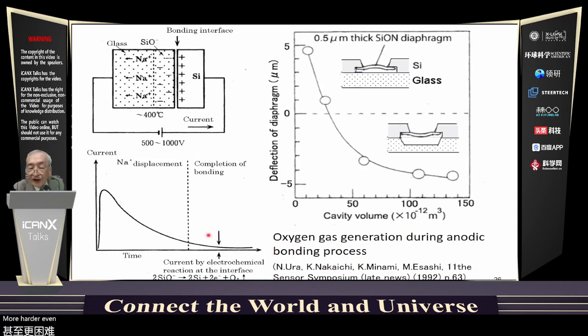This current is caused by electrochemical reaction of the SiO minus at the interface, which generates oxygen gas. The right graph shows the evidence of the oxygen generation. A silicon wafer having thin SiO and silicon oxynitride diaphragms and cavities was anodically bonded to a glass wafer in vacuum.